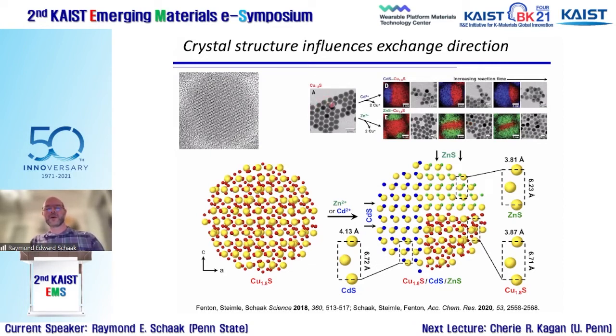So even though these particles are nominally spherical, which are nominally isotropic, so the surface of a sphere shouldn't have really too much differentiation, no major faceting, maybe a little bit, but nothing too significant. These are all single domain crystalline particles. So they're single crystals, and the crystal structure is not isotropic. The crystal structure has directionality to it because it has these close packed planes that are packed, and it has the cations surrounding them.